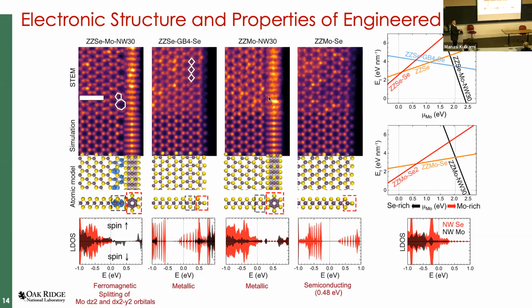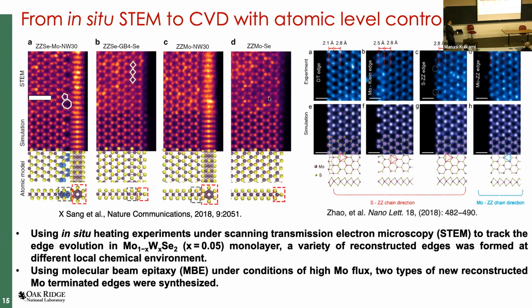So going back to phase diagrams, this is what we talk about when we're thinking about this work. What is the energy of formation, what's thermodynamically stable to form these types of edge reconstructions as a function of our chemical potential? So what we can see in some of these calculations, I'll just point to the top. If you're kicking out the selenium atoms, the moly enriches. So the moly chemical potential increases. And if this increases, this just gives us a thermodynamic estimate of what the most stable form is. And it matches quite well. We're pretty happy with that, pretty interested in that.